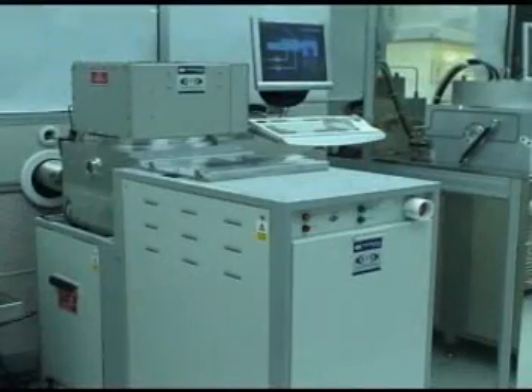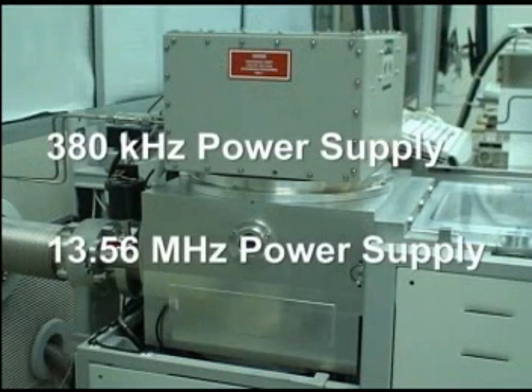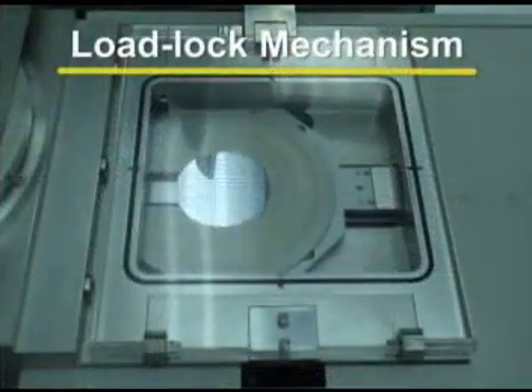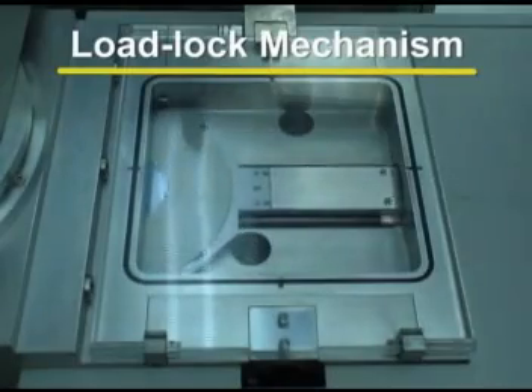The STS PECVD, or Plasma Enhanced Chemical Vapor Deposition System, is used to initiate a controlled reaction between gases and a radio frequency induced plasma in order to deposit materials such as silicon dioxide and silicon nitride. The STS system is capable of operating with both a low frequency and a high frequency power supply, and is outfitted with a single chamber in which all depositions take place. It is also equipped with a load lock mechanism which is used for transporting samples into the chamber.